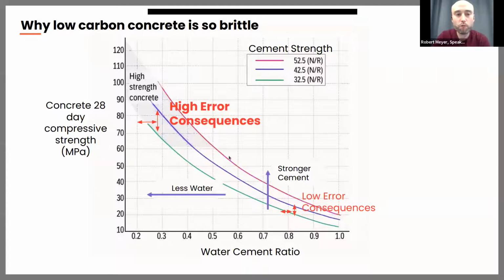And even if I, for instance, get my dosage of water wrong, so if I'm here and I add a little too much, then the consequence in the resulting strength of the concrete is rather low. So basically down here, my concrete is very forgiving. If I make any mistakes in my cement or any mistakes in my water, that's fine. Everything's going to be fine.